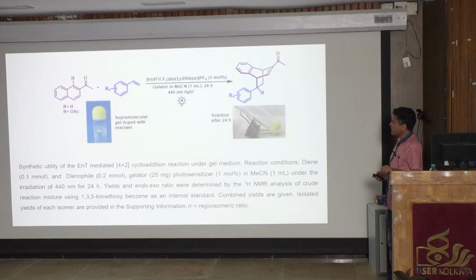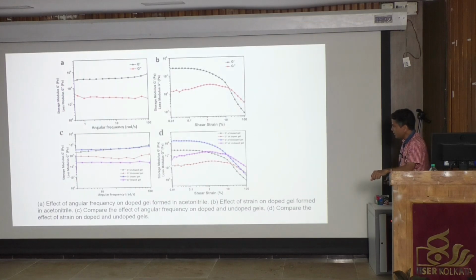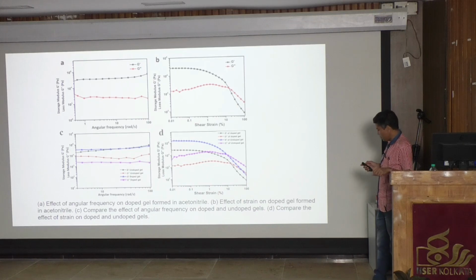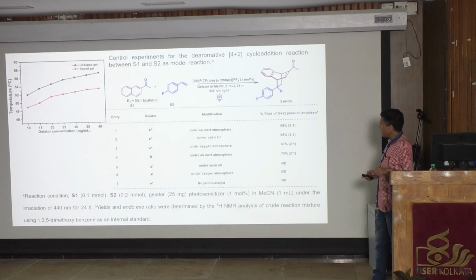The light-sensitive reaction is happening in the gel matrix, and the gel matrix is working as a confinement to do this reaction. So we started with all the rheological studies: before incorporation of the reagent, after incorporation of the reagent, and after the reaction, how the viscosity and rheology of the gel is changing. Then we optimized the concentration of the gelator, and we figured out that at 25 milligram per ml gel concentration, the reaction is happening very nicely.